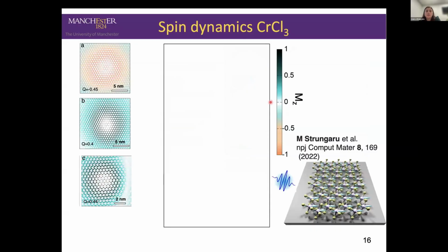One material that we investigated is chromium trichloride, which is a 2D magnetic system with an in-plane anisotropy, as shown in the schematics below. And we were interested to understand whether it's possible to control the spins in chromium trichloride via a laser pulse, via an ultrafast excitation. So for this,